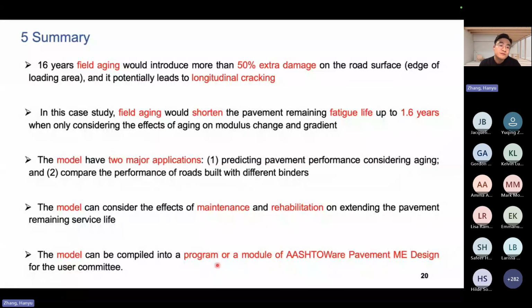In our case study, field aging would shorten the pavement remaining fatigue life by up to 1.6 years when we only consider the effects of aging on modulus change and the modulus gradient. If we consider more, the material degradation in terms of damage tolerance, we'll have much more difference for the aging effects. So our model has two major applications.